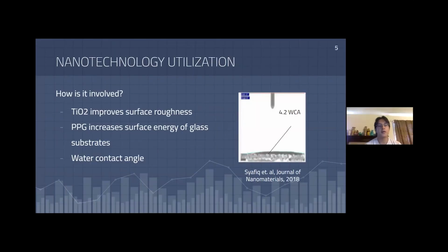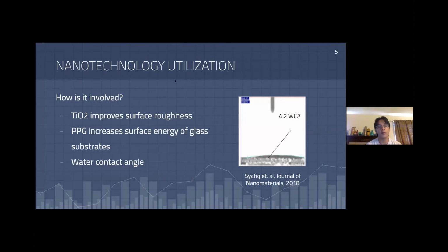And so the way that nanotech is actually utilized in our product is through the micro and nano-sized titanium dioxide particles, which are used to improve surface roughness, and the polypropylene glycol, or PPG, which is used to increase the surface energy of the glass. And when measuring the contact angle, which is just a way to measure liquid surface interactions, it comes to be as low as 5 degrees and can even reduce to 0 degrees after 10 seconds for the coating surface.